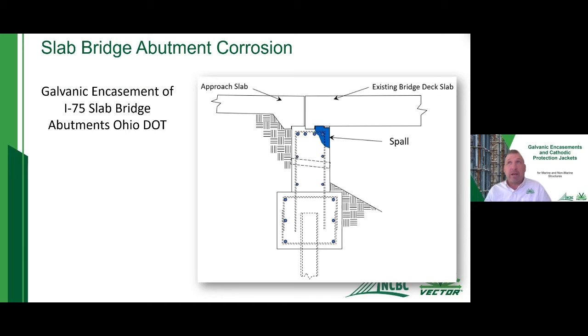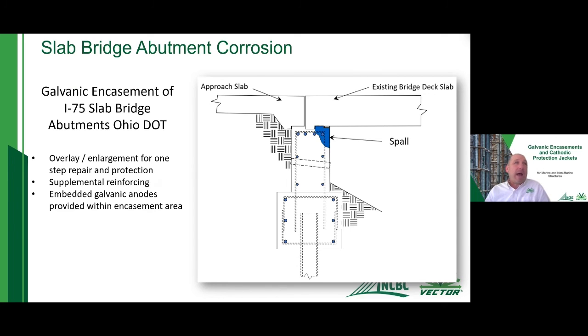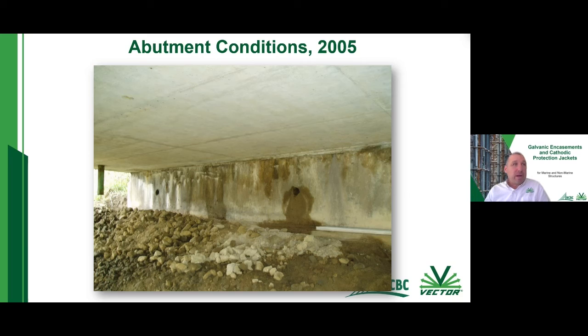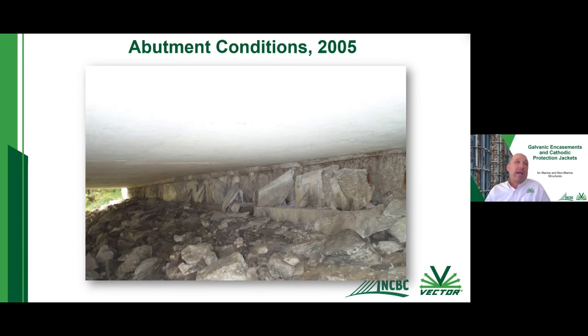So this is just the repair detail for this abutment wall as well. So here they use some supplemental reinforcing along with it, and then they use some embedded galvanic anodes. So in that blue area, they threw a little bit more steel in there, fixed any of the bad steel. And then they threw some small, discrete embedded anodes that went into there. And what ended up happening was it's a very aggressive environment. So even though they addressed the repairs up top, when they came back after doing the repairs, there's a huge amount of corrosion that's still occurring on this abutment wall.